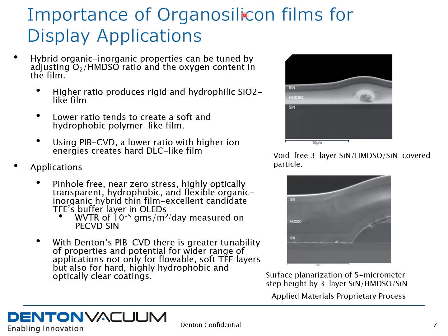The importance of organosilicon thin films for display applications is, as I mentioned before, because of coexisting organic inorganic functional groups that can be tuned to different degrees of hybrid organic inorganic properties by adjusting the oxygen to HMDSO ratio during the process and the oxygen content in the film. A higher ratio produces a rigid and hydrophilic silica-like film, while a lower ratio tends to create a soft and hydrophobic polymer-like film. Using our PIB-CVD process, we could even adjust the ion energies with lower oxygen ratio to tune the composition from a polymer-like to a DLC-like coating.